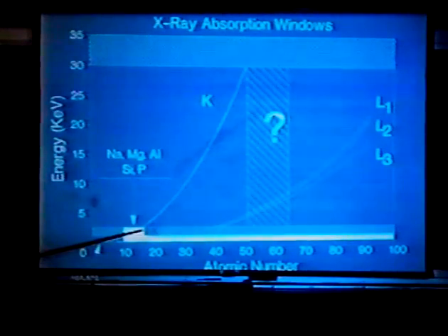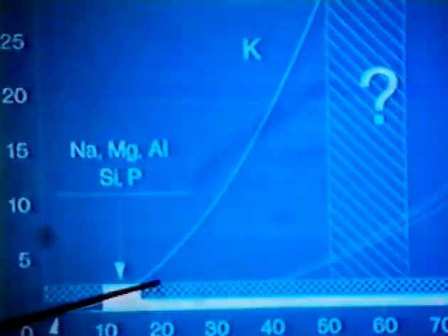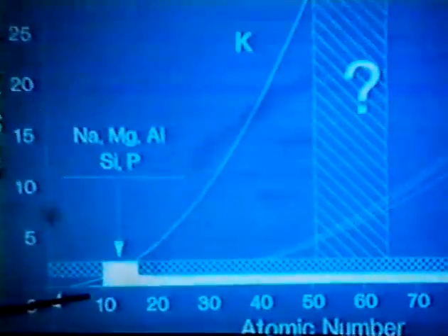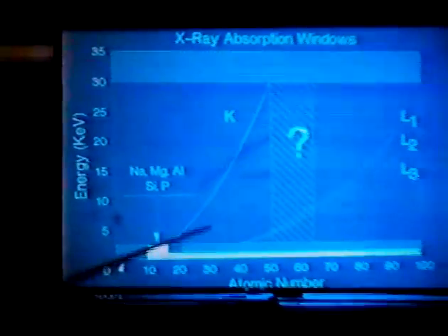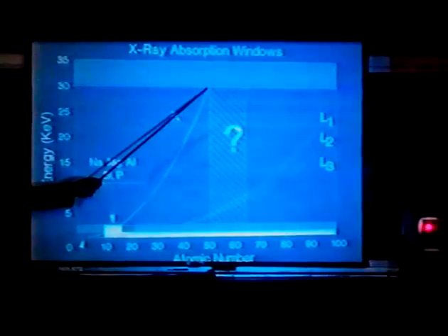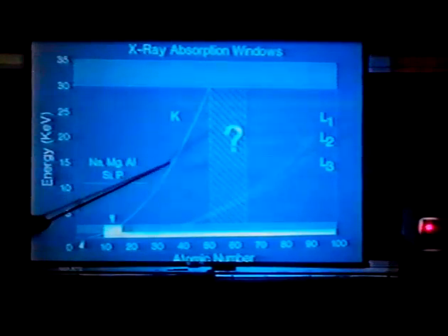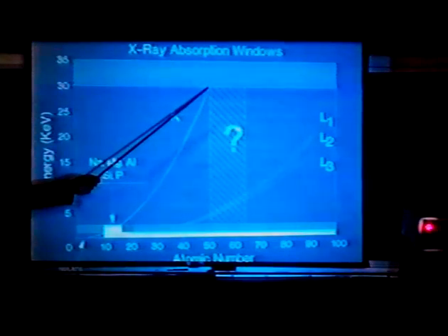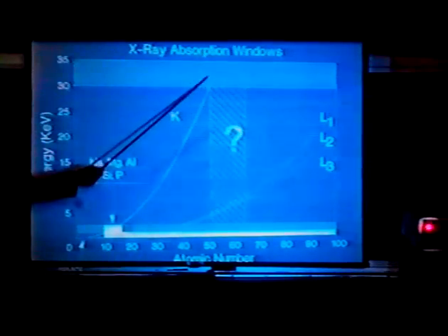I don't know. What I've plotted here is the binding energy of a K edge of a K electron, which is a 1s electron, versus atomic number. And as you go to higher atomic number, this binding energy increases. X-ray absorption spectrum can be collected using these electrons up to about 30 keV. And at that point, the binding energy is really too high for practical purposes.